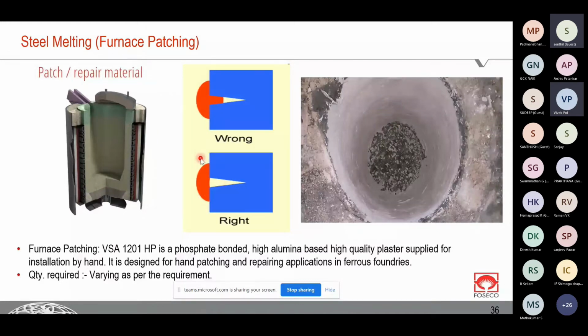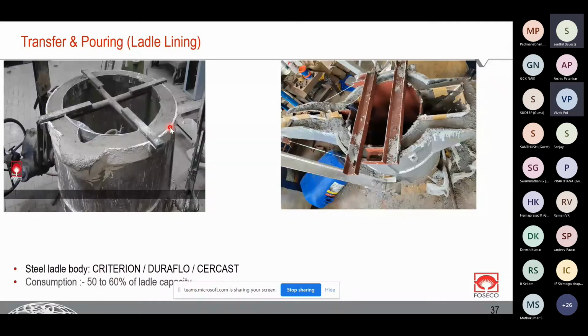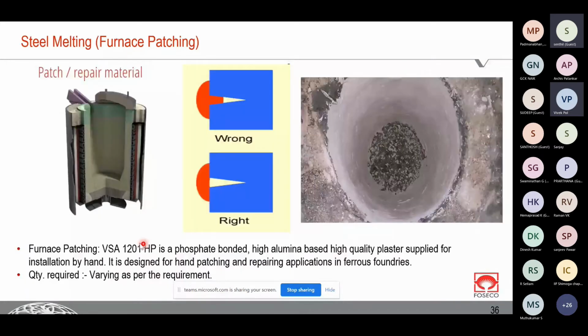So if we fill the crack, then during contraction on receipt of energy, this will exert pressure on the lining, and some more cracks will get generated. So we need to take care of this. We should not fill the crack. And the material VSA 1201 HP is what we recommend for patching application.